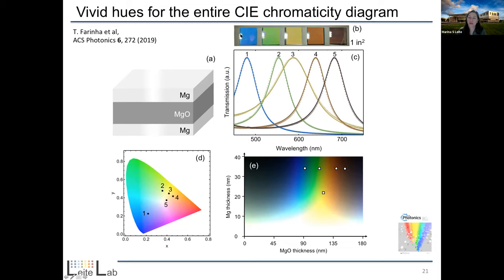This essentially corresponds to the blanks, where we had no metal or dielectric being deposited on a glass substrate. And essentially we could show that it can make colors that vary from blue all the way to a very deep red, a burgundy type of color. It's scalable because it's just a triple layer type of structure. And you can see here the dots correspond to the experiments, the solid line our calculations, and we have a very good agreement between both, as expected, and how much you can shift them.